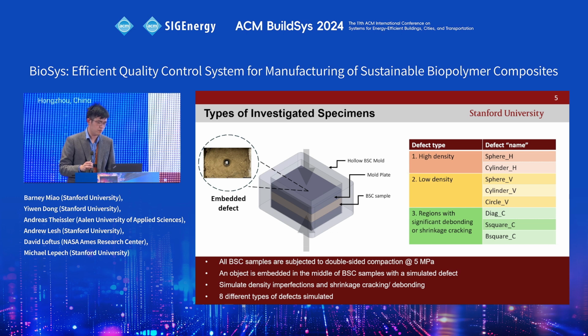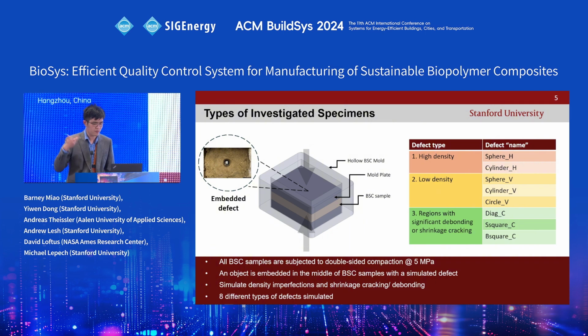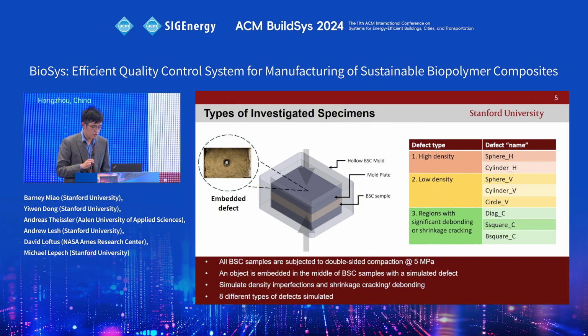Those are typical from mixing issues where you have some clumping of biopolymer, for example. And you also have regions of significant debonding and shrinkage cracking, which is very important and prevalent in material development. So we try to capture a wide range of defects in our study, which is very prevalent in any material development. So we have 8 types of defects versus 1 control sample.